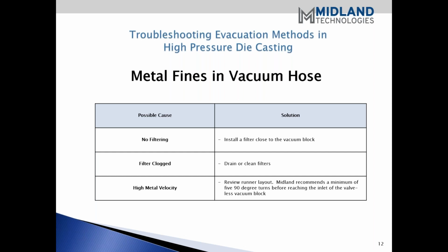And then again, high metal velocity can also cause metal fines in your vacuum hoses. This again goes back to the runner layout and putting in the 90-degree turns and such. Larry, do you have anything else to add with the metal fines? No, other than I experienced those early on. I think almost all jobs I've seen have some fines in them. There's almost no way in the world that you're going to completely eradicate the fines, and of course that's the reason for the filtering. You're going to experience it, but you can minimize it by keeping control of the metal velocity as it goes through the block, at least the amount of it. Right.